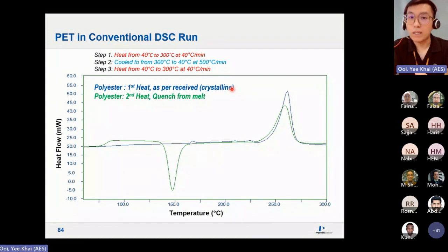But now if I want to make it more amorphous, what I can do is from 300, I cool down very rapidly to 40 degrees again. Then I reheat it again. This is the second heating. Now I can see my Tg. And because of slow heating, it will recrystallize again and then melt again. But of course, because now it is more amorphous, your melting is reduced compared to the first heating as we have seen. So this is why I say for semi-crystalline material, depending on how you heat and how you cool it, you will get drastically different results.